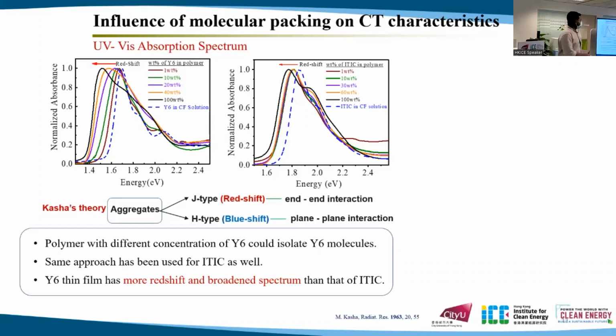This redshift and blue shift are actually caused by the formation of different dimers, J-type and H-type dimers. If the Y6 molecules have more end-to-end interactions, then they form J-type dimers, which show a redshift. And if the Y6 molecules have more planar interaction, like face-to-face interaction, then they form H-type dimers, and it shows a blue shift.